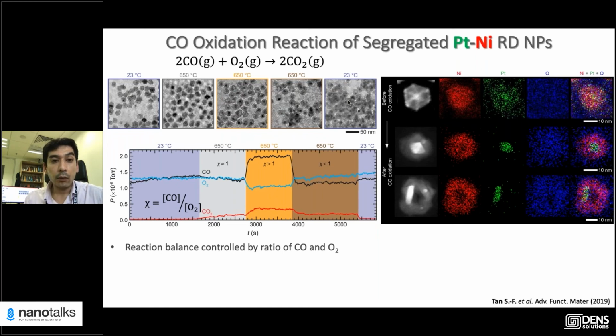So what happens is when you start a reaction, the first thing is that your nanoparticle phase segregates. The nickel ends up on the surface, the platinum core phase segregates, or in some cases you also form voids. Here, for example, you have voids, but some nanoparticles don't have voids, so there are two possible outcomes. The voids can be explained through the Kirkendall effect that I talked about earlier. But the key thing is you end up phase segregating, and the surface is mostly nickel oxide, and most of the platinum segregates into the center.